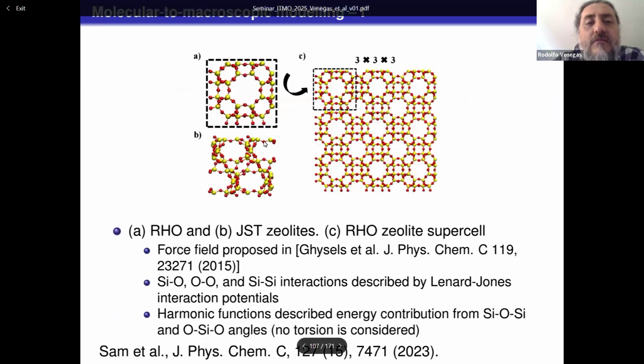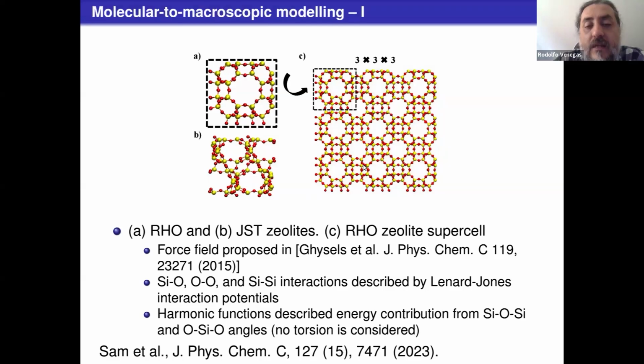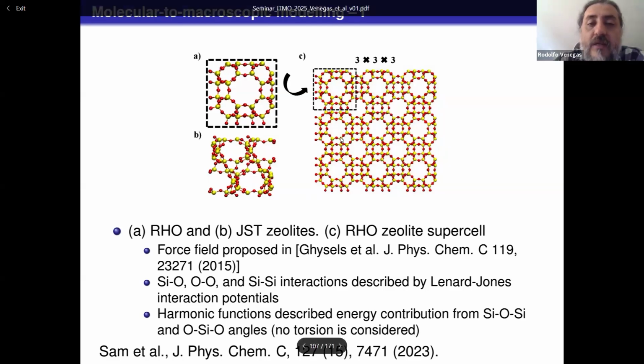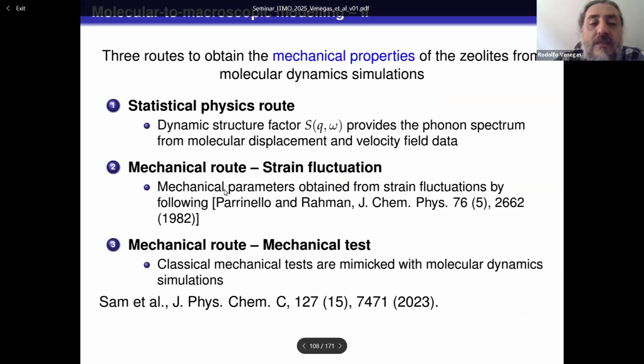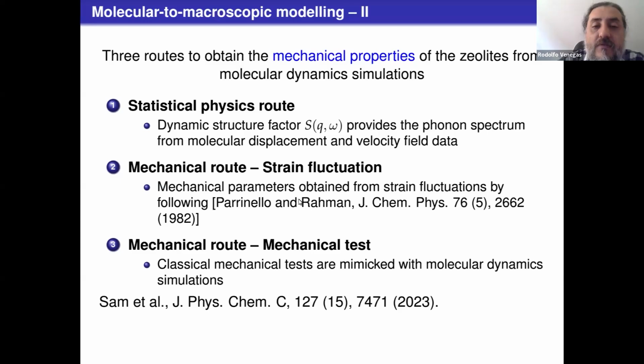So our work related to molecular-to-macroscopic models, I will skip a few slides just to give an idea. The idea is to simulate and solve these problems with molecular dynamics, to estimate the elastic parameters of this zeolite structure. And we used three different routes. One of them is a statistical physics route, that is basically related to the fitting of the dynamic structure factor. A mechanical route mimics the classical molecular dynamics extension and compression test. And a strain fluctuation route based on the work of Parrinello and Rahman, where from the strain fluctuations we work out the mechanical properties of these materials.